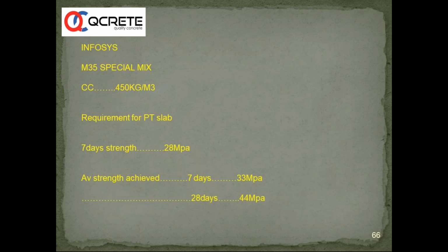In Infosys, the mix was for a PT slab actually. So they specified a 7-day strength of 28 MPa. And generally we used to get about 7 days of 33 MPa and 28 days 44 MPa. So here what we need to see here is with OPC plus fly ash, we can get adequate 7-day strengths also, even though traditionally OPC fly ash mixes are slower in gaining strengths up to 7 days.